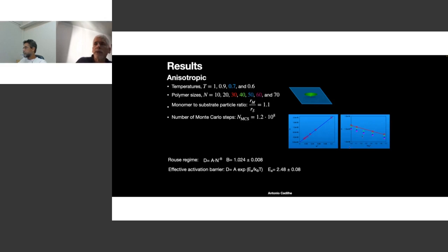But, on the other hand, these transitions on the right side, the diffusion coefficient as the logarithm of it as 1 over kBT. So this is Arrhenius behavior as defined in the last line, and it shows that there is an energy barrier for transition that is given by that number.